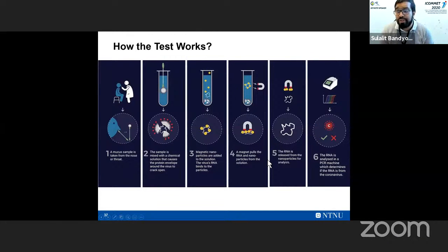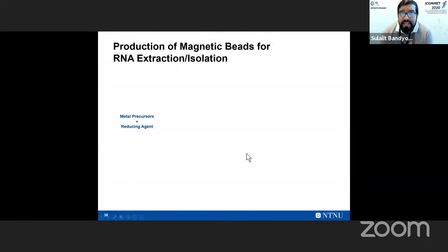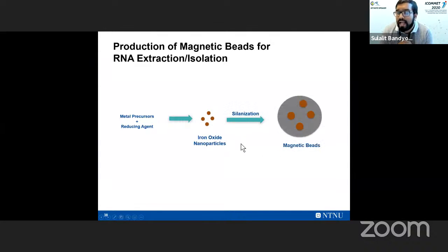So our contribution to this method has been the development of the nanoparticles and, most importantly, the scaling up, because it's not about testing a few people, it's about testing the whole Norwegian population. So the basic principle is still the same as I mentioned before. I cannot give you more details about the exact process due to confidentiality, but what we use is metal precursors and a reducing agent. We synthesize these iron oxide nanoparticles, and then we coat them with a silica layer, forming these magnetic beads that are used for the corona diagnostic.